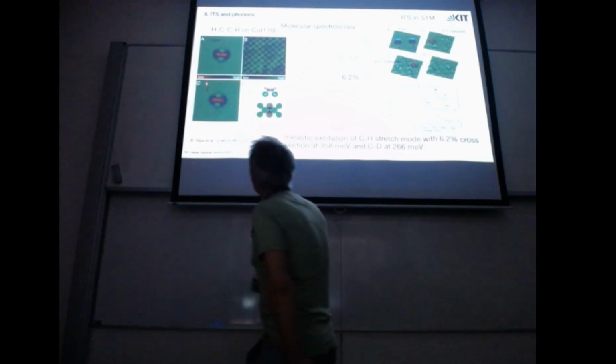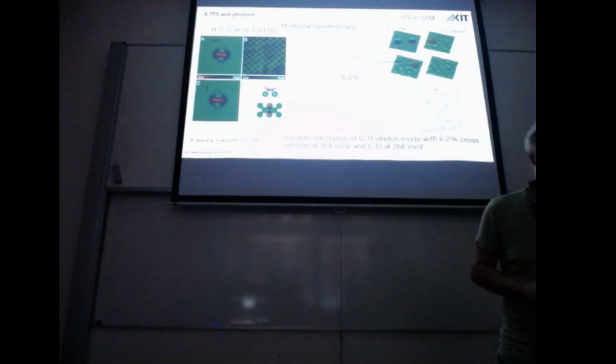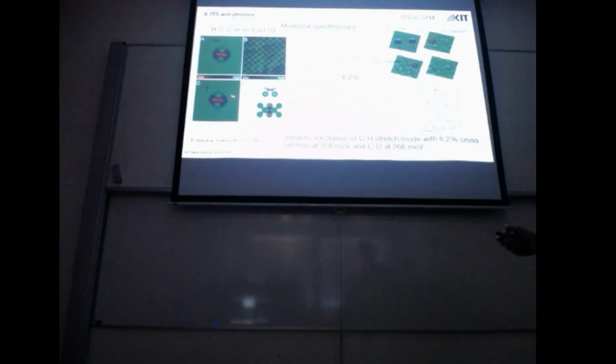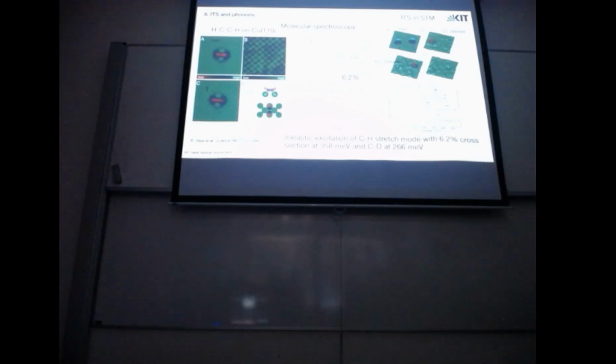Okay. 1 is the spectrum on the copper, 2 is on the molecule. Sorry for my colors. This is I-V. Of I of E, hardly anything can be seen. They look almost the same, and if you take the difference of them, at the noise level of the STM, you can see nothing. But you can increase the sensitivity by the lock-in technique, the dI/dV.